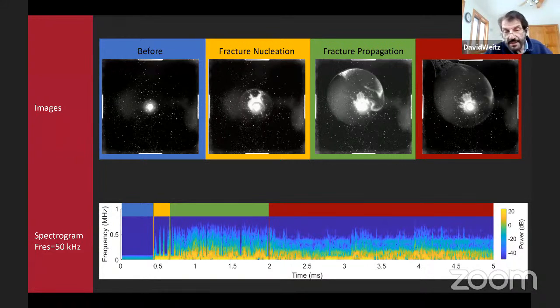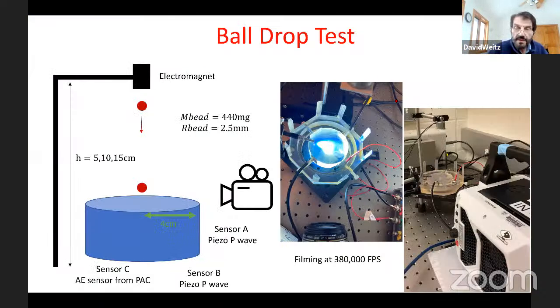So for example, we could take that signal, and that was an early signal, but we could take it and look at the different places: the nucleation, the fracture, and the flow. And we can do a running FFT. So we take spectrograms, and instead of plotting the amplitude as a function of time, we plot the frequency spectrum. And you can see that there really does clearly look like there are some fractures occurring, some sounds occurring right where the crack is propagating. And we get a different signature as the fracture propagates beyond the nucleation, and a different signature still again when the fluid is flowing.